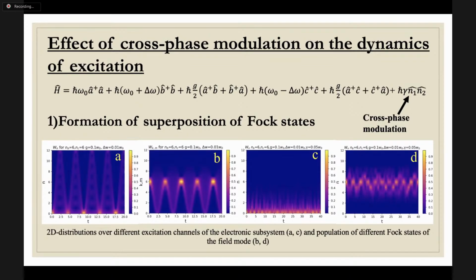The slide shows two-dimensional distributions over different excitation channels of the electronic subsystem, figures A and C, and populations of different Fock states of the field mode, figures B and D. In the case of absence of nonlinearity, it's A and B, and in the presence, it's C and D. The cross-phase modulation is seen to play a negative role and suppress the excitation of highest channels. At the same time, a very non-trivial field state is formed during the interaction, which is characterized by population of Fock states neighboring the initial one.